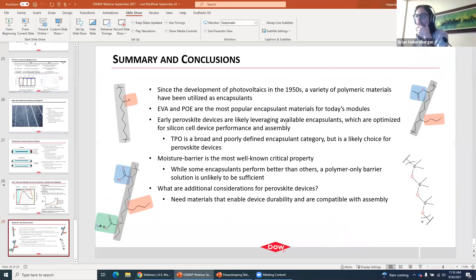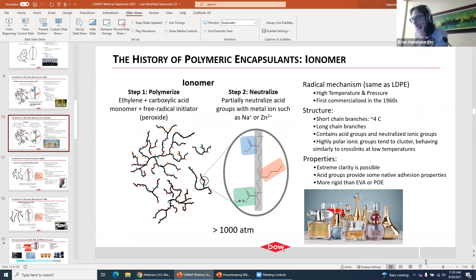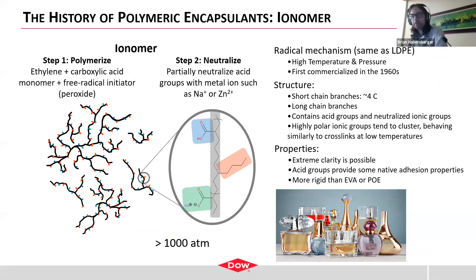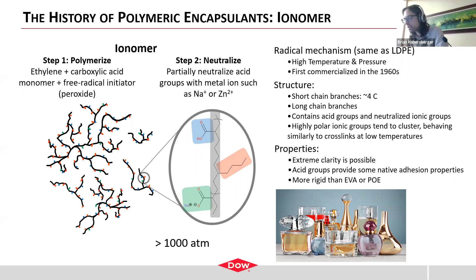Ionomer has been approached in a couple of ways. It can be used as a standard encapsulant, where the standard thickness is about half a millimeter — maybe 0.45 mm is a standard thickness. I've also seen some who have tried to apply ionomer as an additional thin layer combined with an EVA encapsulant to provide some barrier property to the system. In general, the thickness of all the different materials is relatively standardized at about half a millimeter. Glass-glass devices often use a slightly thicker encapsulant standard, I think to provide accommodation because glass is not compliant — you can get close contact between the electronic components and the rear glass relative to a backsheet device.